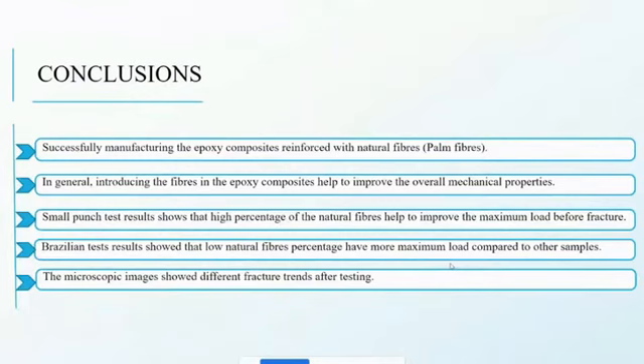The conclusion is that we successfully manufactured the epoxy composite reinforced with natural fiber, which is a good start for our future study. Also, in general, introducing the fiber into the epoxy composite helps to improve some of the overall mechanical properties. The small punch test results show that a high percentage of natural fiber helps to improve the maximum load before fracture. Brazilian test results showed that a low natural fiber percentage has a higher maximum load compared to the other samples. And finally, the microscopic images showed different fracture trends after testing.